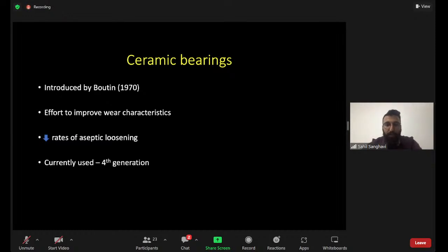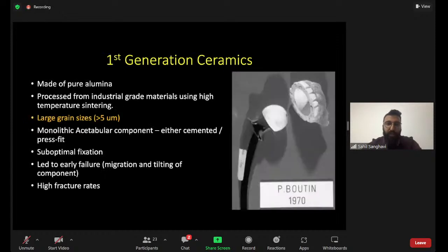Currently, we are using the fourth generation of ceramics. So what are these four generations of ceramics? The first generation of ceramics was made out of pure alumina, and it had a large grain size. That was the main drawback of this ceramic, because this large grain size was actually responsible for high fracture rates. In addition, first generation ceramics had monolithic acetabular components, which were either cemented in directly or fixed in a press fit manner. However, they had suboptimal fixation, which again led to failure of these implants by either causing migration of the implant or tilting of the acetabular component.